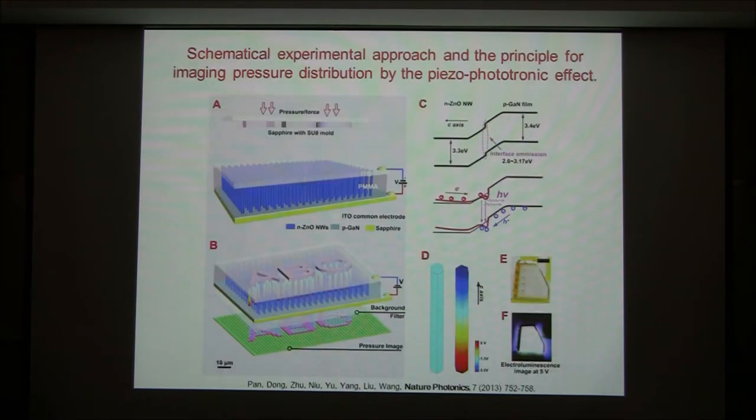We're not only satisfied with one LED, but we manufactured 22,000 nanowires, and the root of each is a zinc oxide gallium nitride interface, each with an LED emitter. So you can see, if you apply a stamp to this, the stamp can change the barrier height locally, so the emission light will be different. If you vary from one pixel to the next pixel, you can use the emitted light to detect the strain applied locally. Why? Because the depth of this charge channel determines the strain applied, determines the piezoelectric effect.